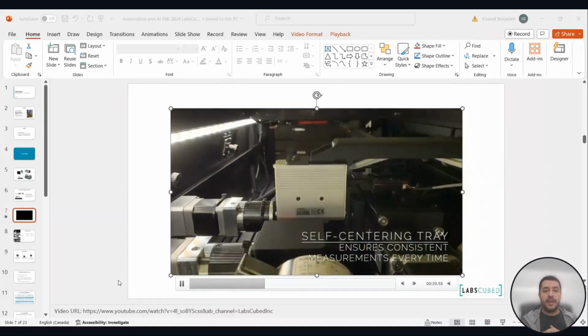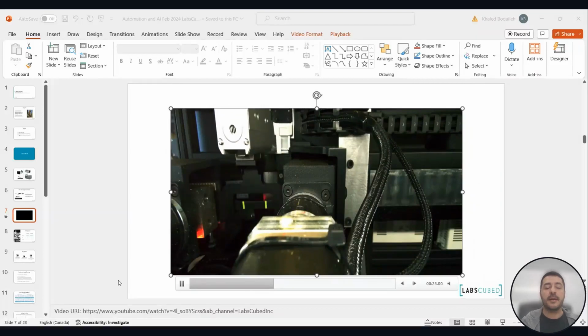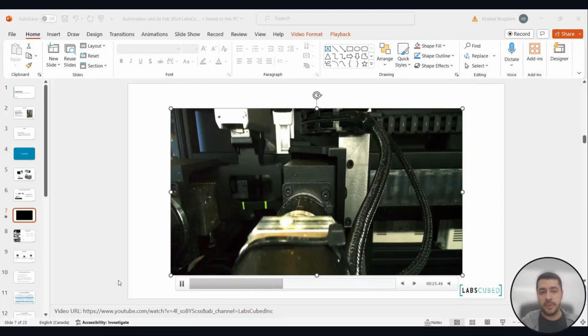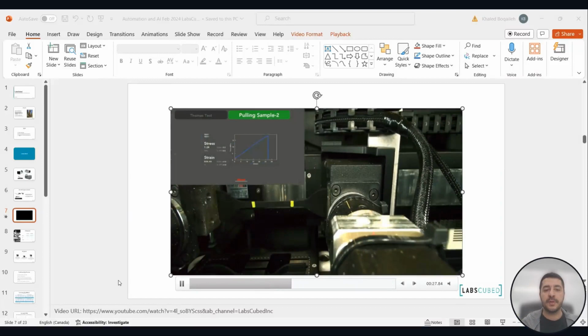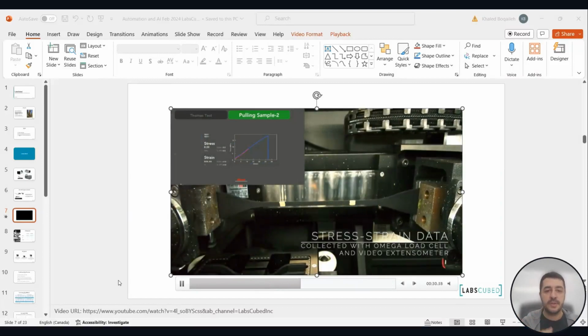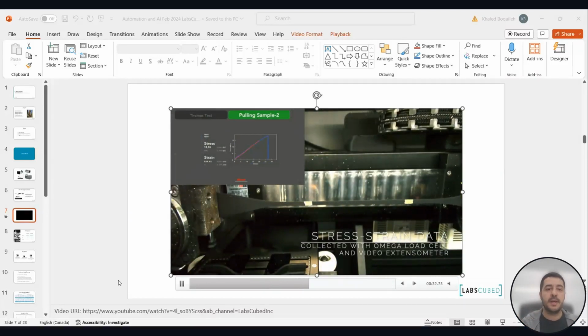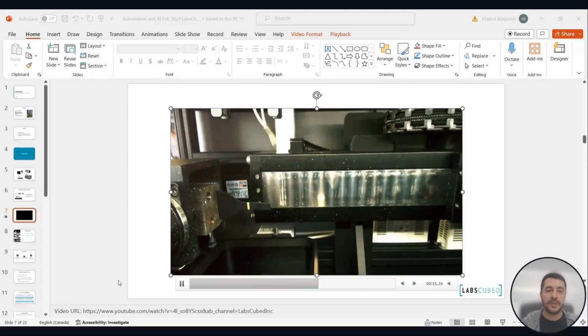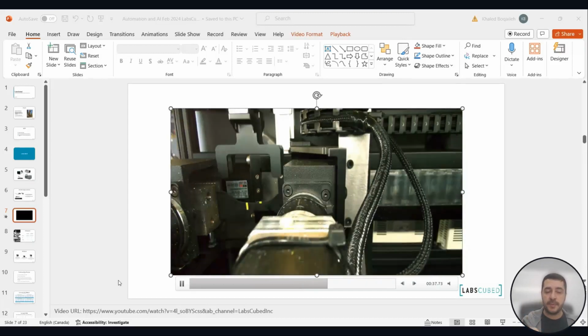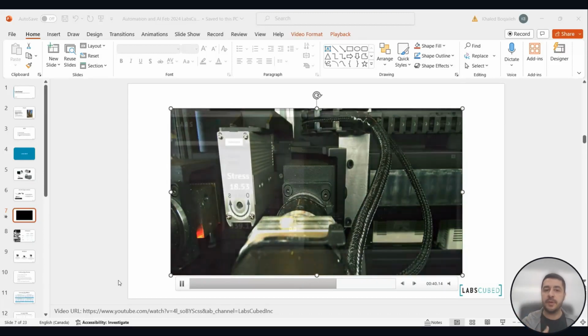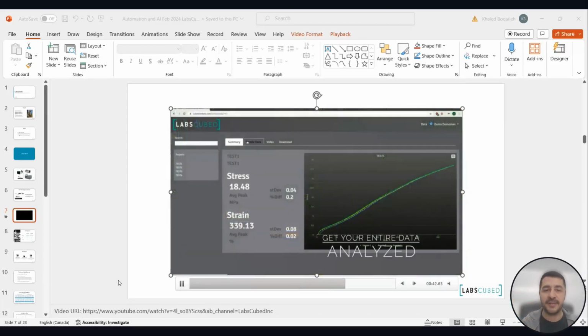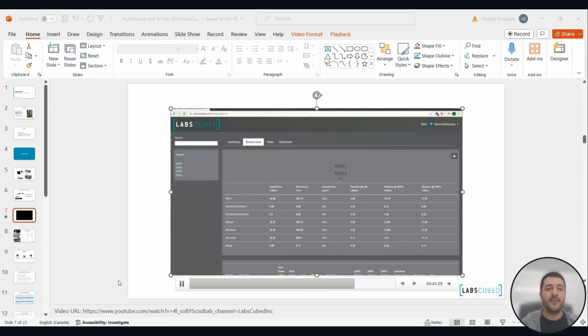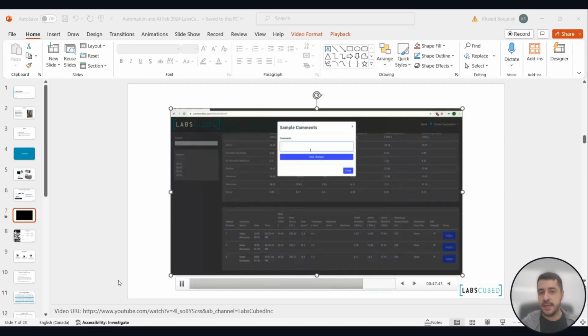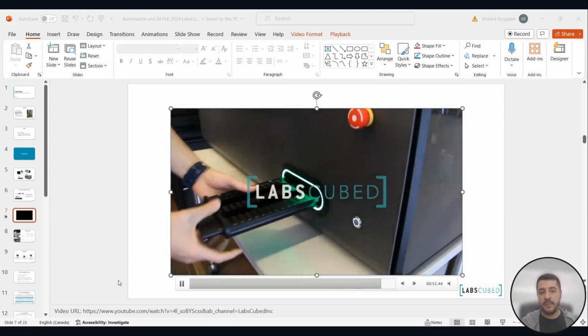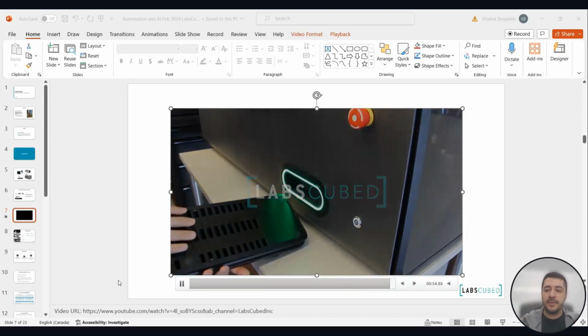And effectively the machine will go down, pick up each sample separately, put it into the grips, and then pull it apart as a normal tensile sample. And then we use a vision system to measure the elongation. So you see those 2 marks, it's measuring those as it gets pulled, and obviously a load cell as well to measure the force. Once that sample is done, it gets dropped off in a back bucket, and then the machine would continue through all your samples while you're not standing there doing one at a time as people usually do. Once that's completed, all that data goes into a database, or your own internal or external existing database. The data can also be put in there as well. Once you're done, you just throw out your samples and it's all good to go.